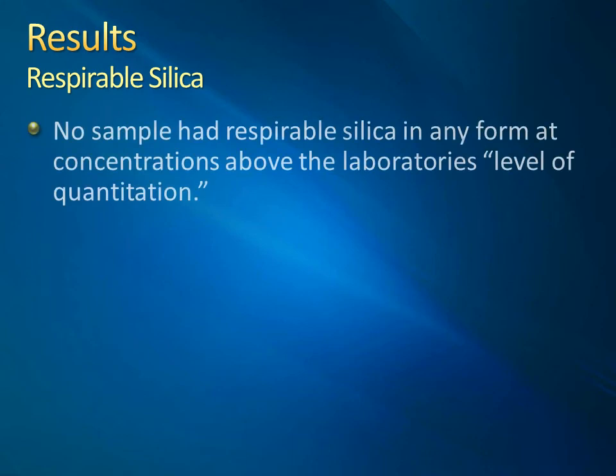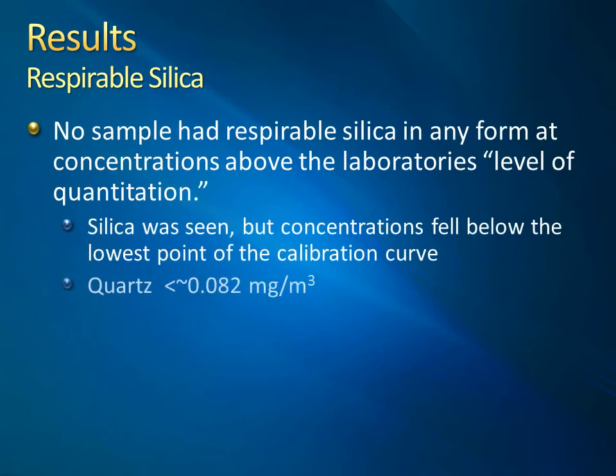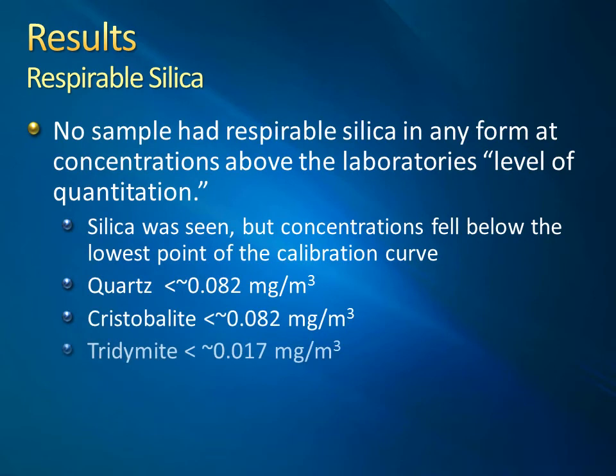For the respirable silica assay, no sample was found to have collected any respirable silica in any of the three crystalline forms within the quantitation limits of the laboratory. That is, silica was seen in the sample, but the concentrations were below the calibration limit. This was unexpected, as the high operation temperature of the furnace, the 1450 degrees Celsius versus the 660 required to melt the aluminum, was reasoned to be a factor in the creation of multiple crystalline silica forms.